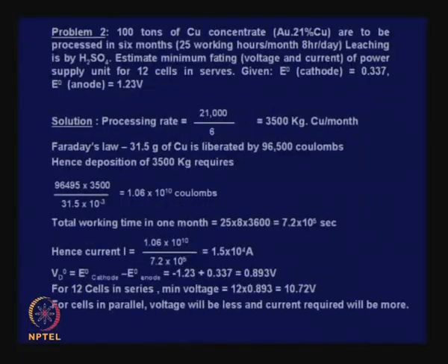You are passing the current to dissociate a compound, but it is very difficult to restrict the role of the current only to that dissociation reaction. The current can go elsewhere for some side reactions. So, there is wastage of current, and that is why the current efficiency falls below 100. But then current efficiency values, if you see, are always better in low temperature operations.